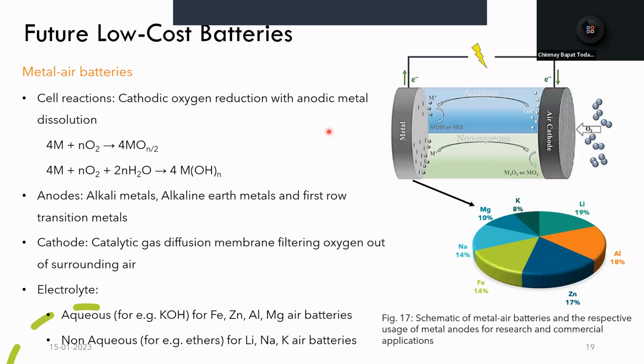However, research is also being focused on making these reactions reversible so that we can either have a battery chemistry similar to sodium-ion batteries, or we can take out these exhausted metal oxides and extract pure metals from them and recycle them. So for the anodes, we have alkali metals and alkaline earth metals such as potassium, lithium, sodium, etc., and also first row transition metals such as iron, zinc, aluminium, etc. For the cathodes, we have basically a catalytic gas diffusion membrane, which filters out the oxygen from the surrounding air, and this oxygen can then react with the metals as we see in the reactions.